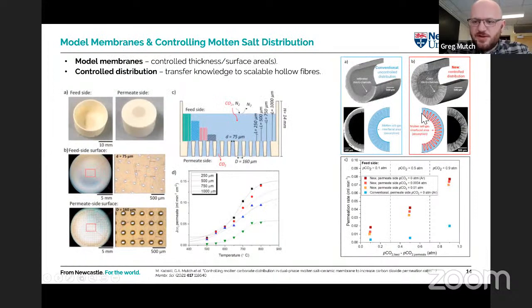Whereas in this image, we've deliberately left a lot of open porosity, and the blue color is the molten salt. And this allows us to have a very high surface area for desorption, which we know is the rate limiting step from the model system. And then when we look at permeation rate, we see that we can get higher permeation rates. So we use a model system in the lab, a very simplified structure that is never going to be a scalable membrane, but it tells us information about how the membrane operates. And then we use a real, scalable membrane structure, and apply that knowledge to make membranes that are more useful for real applications.